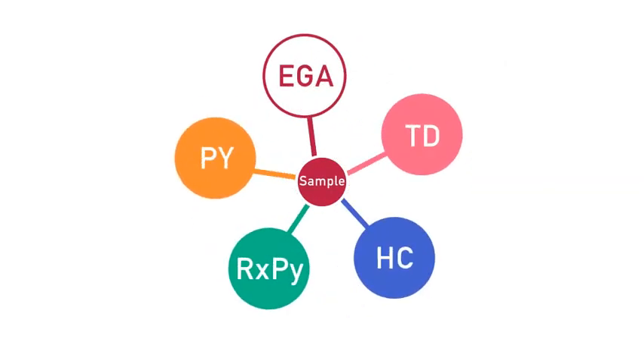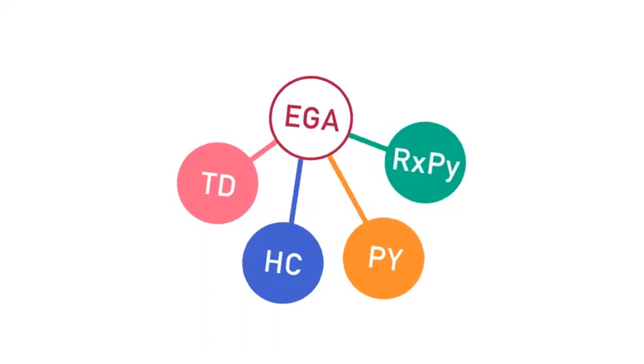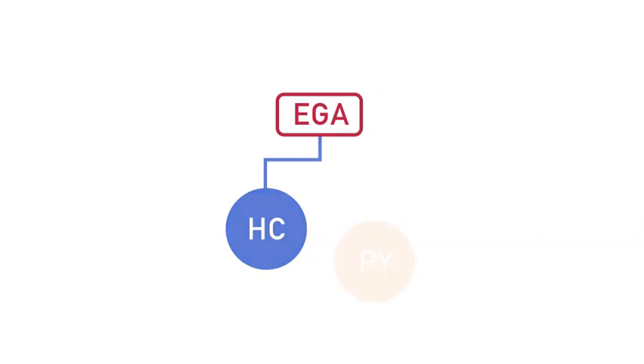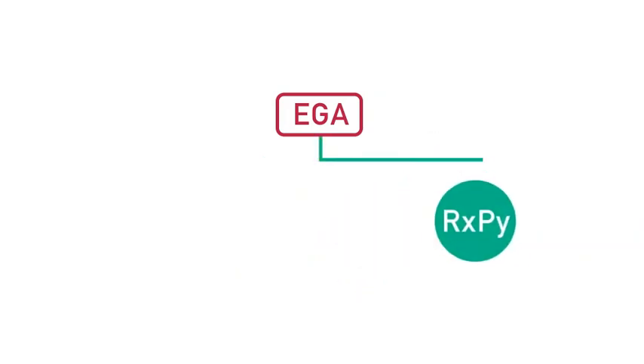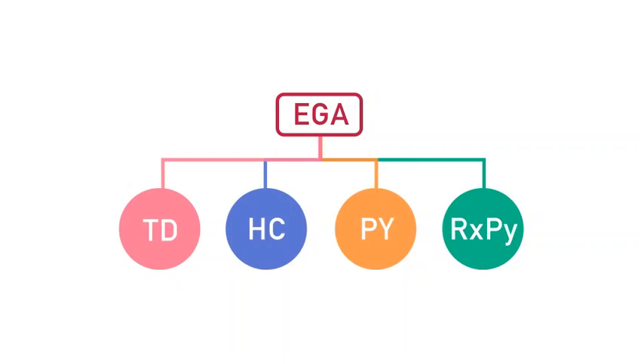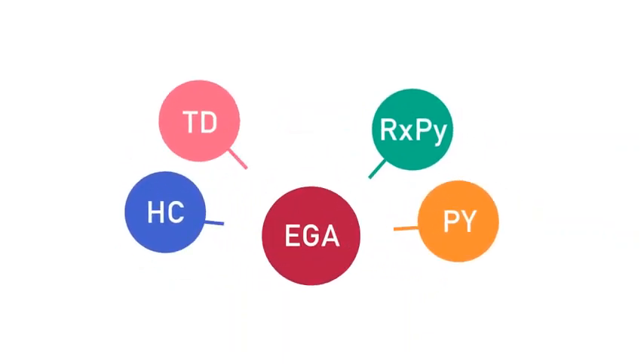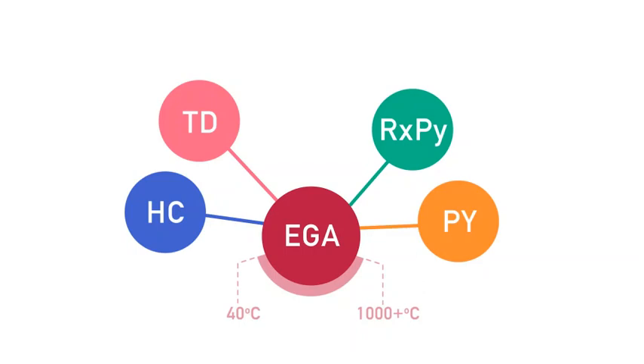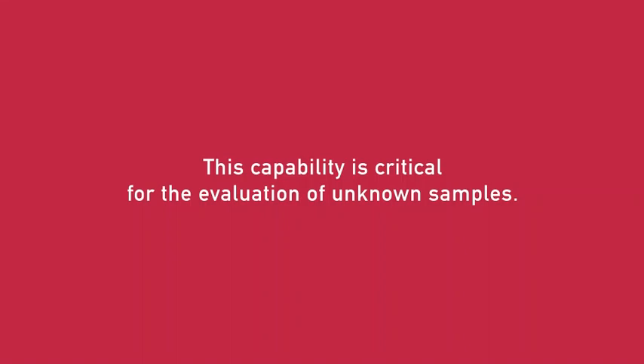The first step in creating the method map is evolved gas analysis, or EGA. A full-range EGA is performed using the microfurnace technology to obtain the thermal profile of a sample for light compounds, volatiles, and additives, as well as oligomers, heavy, polar, and polymeric compounds. The EGA experiments can be done from 40 degrees Celsius to over 1000 degrees Celsius and correlate results to well-established thermal gravimetric analysis techniques throughout the entire temperature range of the experiment. This capability is critical for the evaluation of unknown samples.